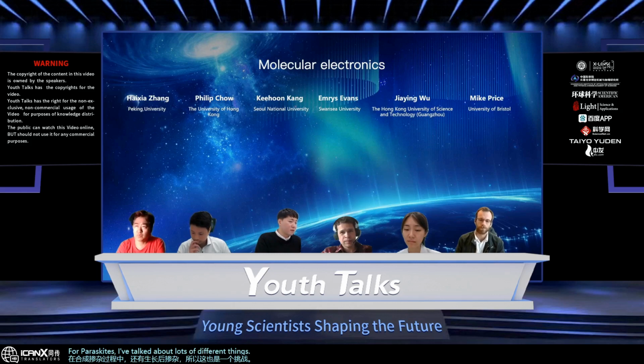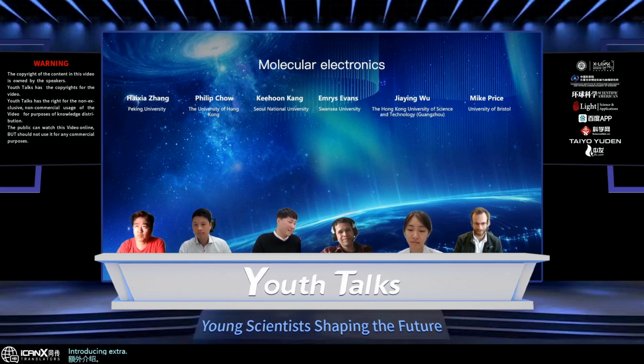For perovskites, I've talked about lots of different things, but molecular doping probably, for the same reason, the binding energy is so small, it's the only option, and therefore making it industry applicable is going to be very difficult. So we need to really play around with the crystal structure, by replacing some ions as dopants in perovskites, but also dealing with the fact that in perovskites the ionic motion is really large. You need to think about passivating defect sites, as well as introducing extra, replacing heterovalent atoms. So the challenges are a multitude, but that's my current opinion on what would be the optimal doping for this range of different materials.